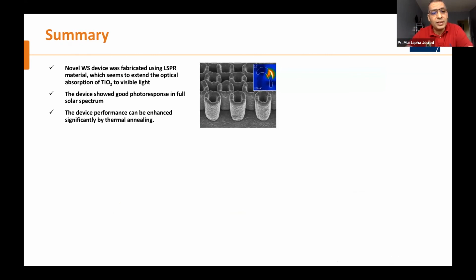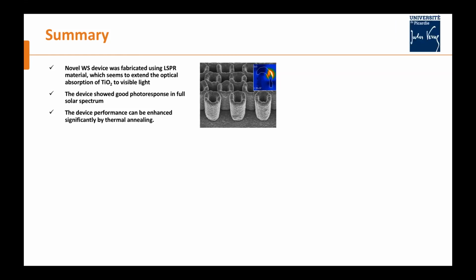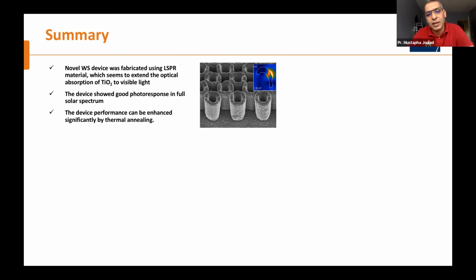So as a summary, I come to my conclusion. I hope that I was able to show you that a novel water splitting device was fabricated using LSPR material, which seems to extend the optical absorption of titanium dioxide to visible light. This is one of the first interesting things about this device. The second thing is that the device shows photoresponse in the full solar spectrum, and also its performance can be enhanced just by thermal annealing. This is very interesting, because it means under the sun, the heat will also take advantage of this device.